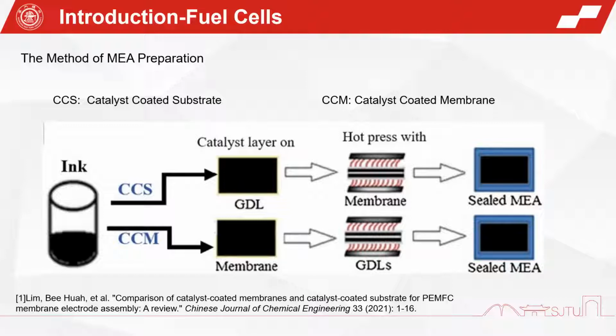However, such a CCM method is difficult to apply to the MEA for high temperature PEMFC. For the conventional PA-doped PBI membrane used in high temperature PEMFC, after the PBI is doped with PA, the swelling rate is as high as 150 to 250%, and the mechanical stress is significantly reduced. If the MEA is pressed by the CCM method, the cathode layers are prone to peel off due to excessive swelling and the soggy surface of the membrane. Therefore, the CCS method is routinely used to develop the MEA for high temperature PEMFC.